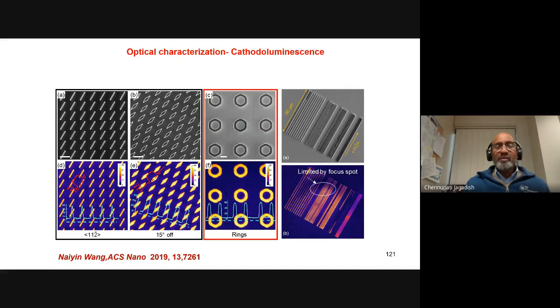And here is a cathodoluminescence image, because cathodoluminescence is something which we do in an electron microscope. You excite the nanostructures with the electron beam rather than a laser pulse, and then you generate electron-hole pairs and look at the light coming out of these. You can see the beautiful bright, very uniform light emission, indicating that Naiyin Wang's hard work of 4 years really paid off. You're able to get very good and very uniform light emission, indicating that they are defect free and things like that.